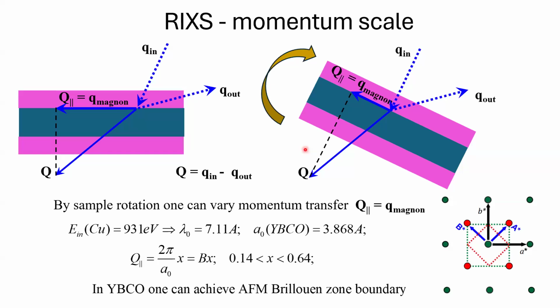The next important advantage of RIXS is the momentum scale. Here we see the momentum of the RIXS photon which we use, at 931 eV, which has this wavelength, and it gives us the possibility to move through the momentum space of the crystal, with a given value of the length, which one can achieve here, even to the boundary of the antiferromagnetic Brillouin zone.